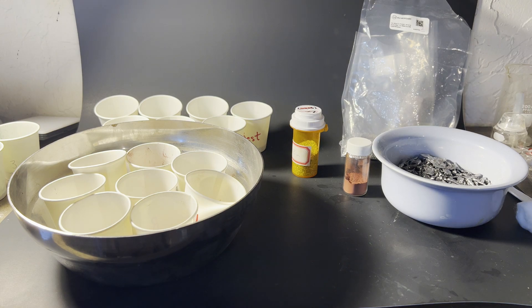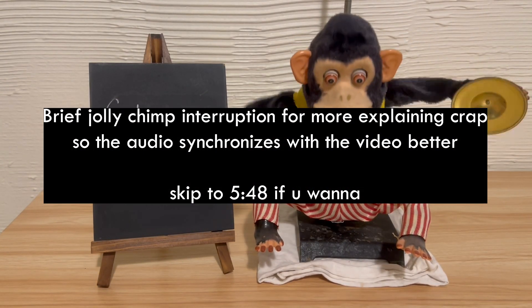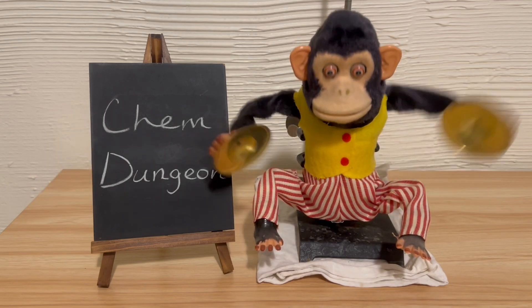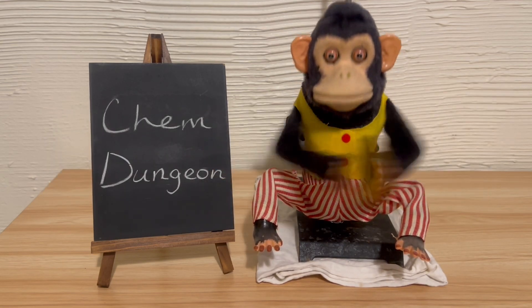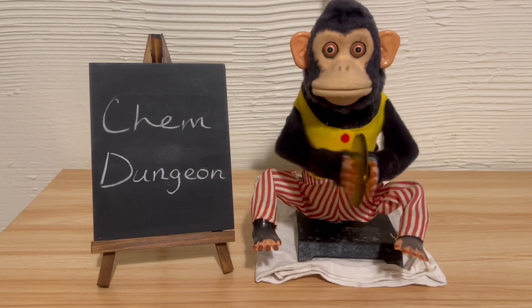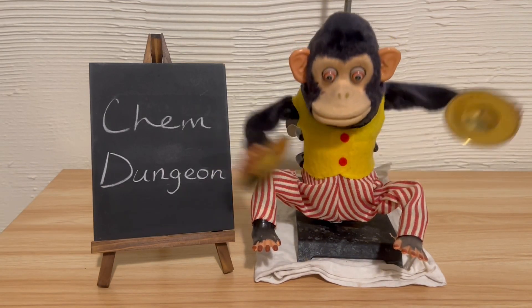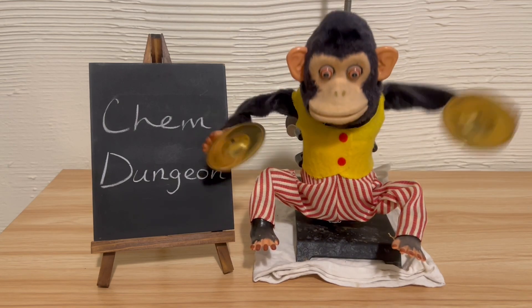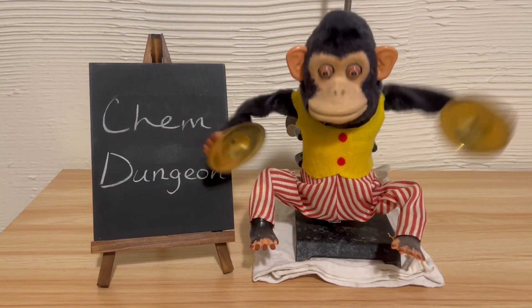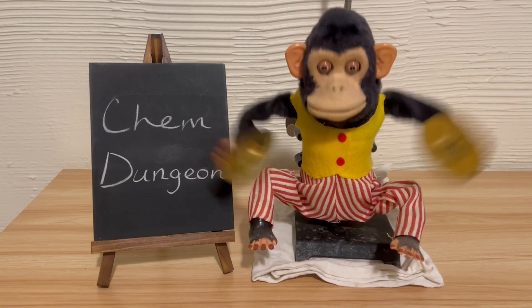Weighing all this out beforehand was not very smart in retrospect, as I didn't realize how poorly suited copper powder is for making alloys when I made them the way I ended up making them. I thought the copper would just settle to the bottom and blasting it with torches wouldn't blow it everywhere, but I was wrong. For a few of the ones I remake I used some very small copper shot and it works perfectly. It also would have been better to melt the tin first then add the alloying metals.